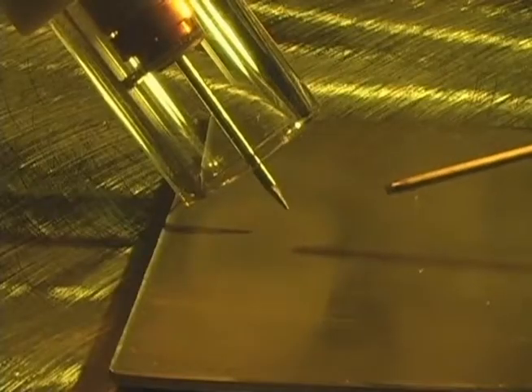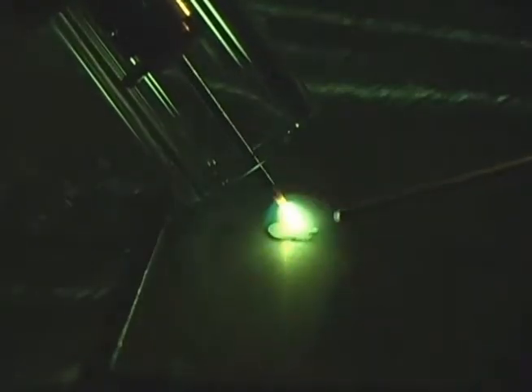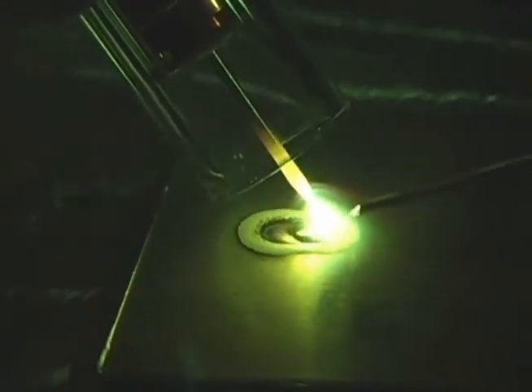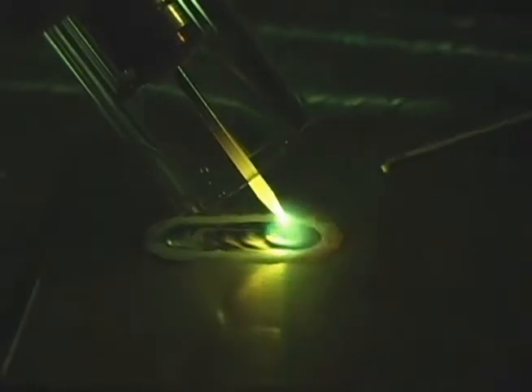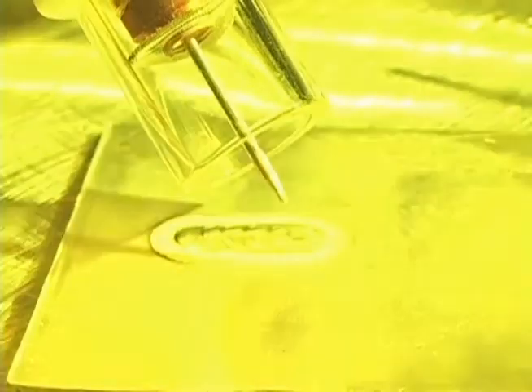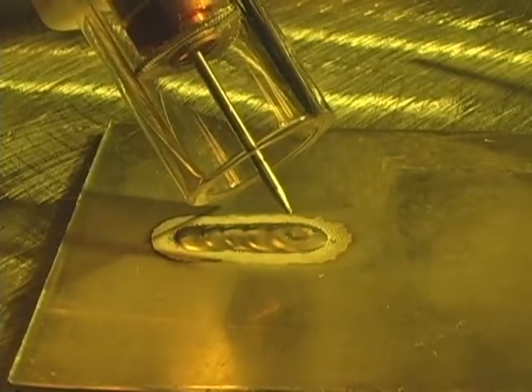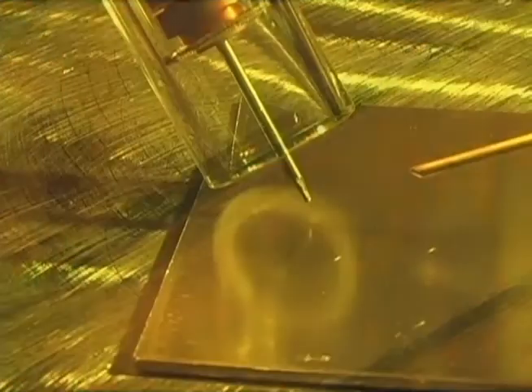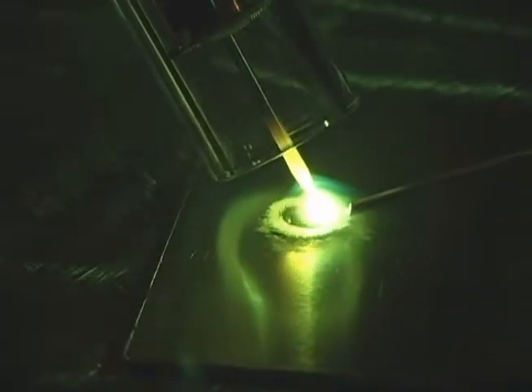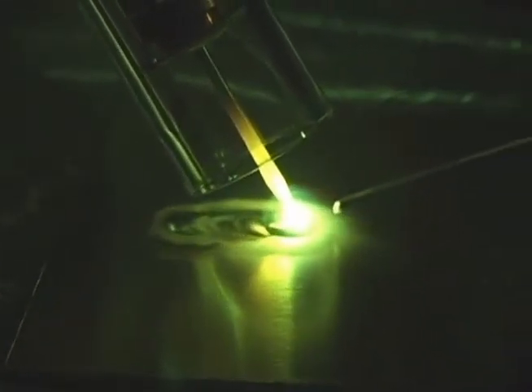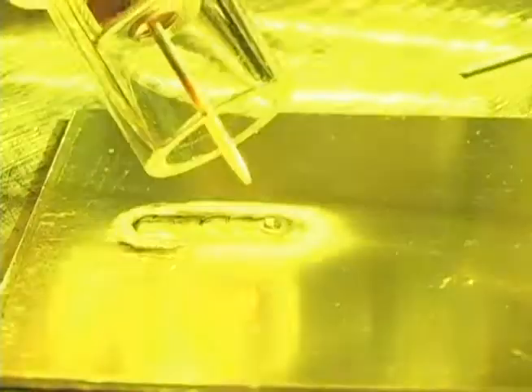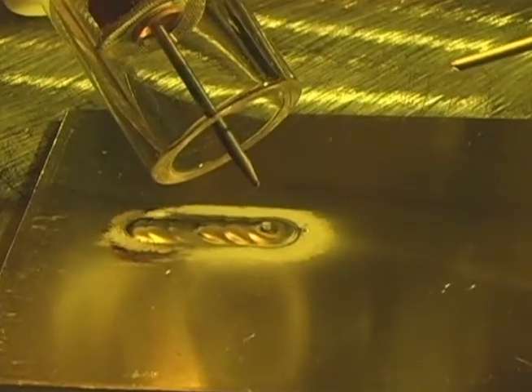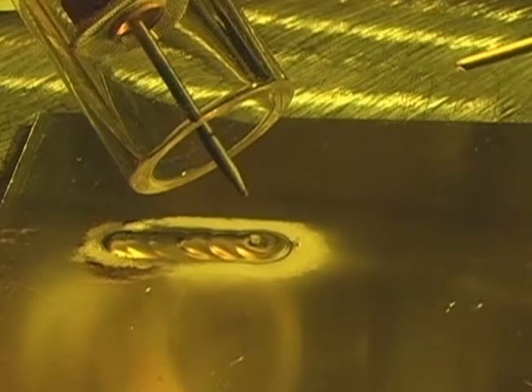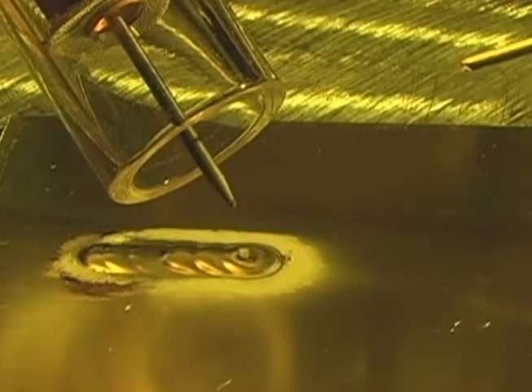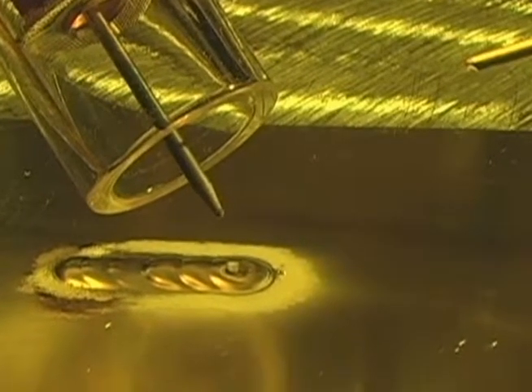We would like to show you the effect of post-gas. First example is enough post-gas. 1/16 inch tungsten, red hot, cools completely while the post-gas is flowing. The second is not enough post gas. The gas stops and the tungsten turns black. If you have discoloration in your tungsten and you did not contaminate it by sticking it in the puddle or hitting it with the filler metal, then you are probably not running enough post gas.